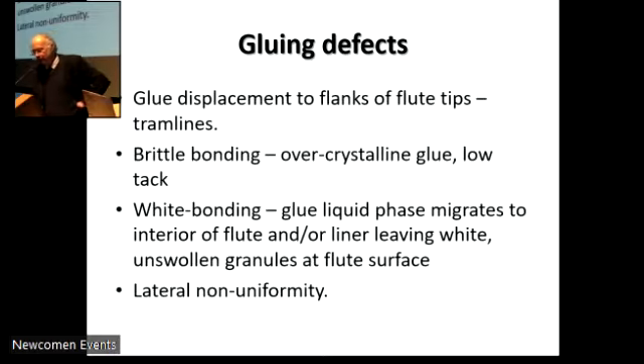You can also get defects arising from the gluing process itself, displacement onto the flanks of the flute. So there's actually a very limited contact area for the glue to operate on. That suggests that the glue is perhaps not of sufficiently high viscosity. You get this problem of brittle bonding, and that's when you've got too much heat going into the system and the glue is cooked off even before it hits the liner board that's coming in to meet it.